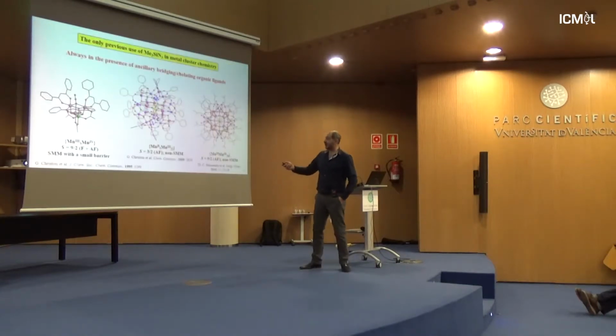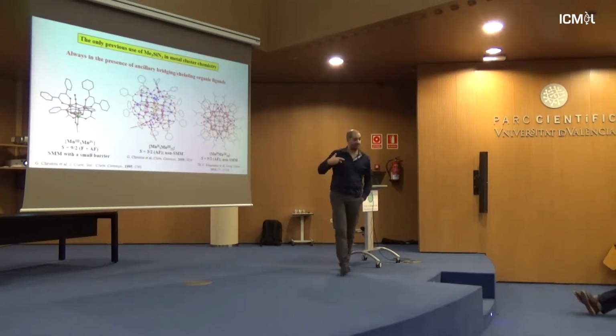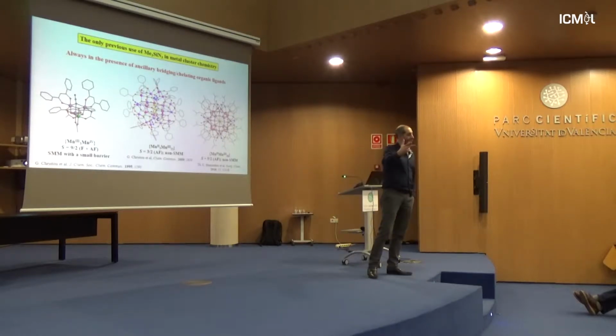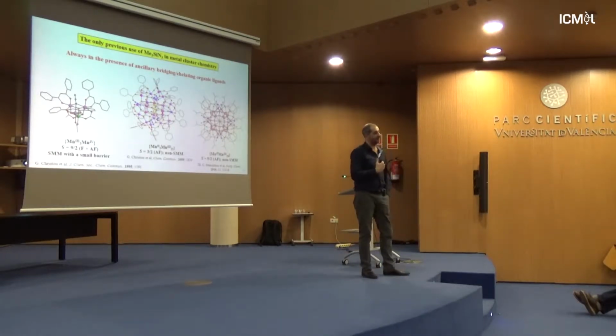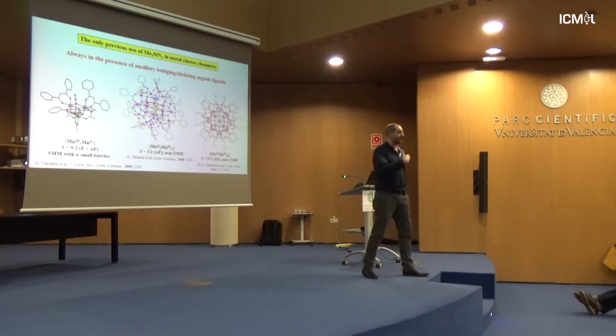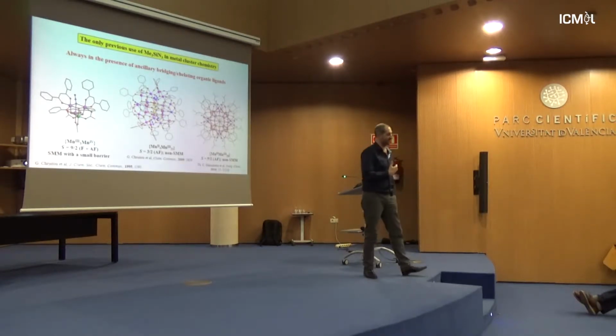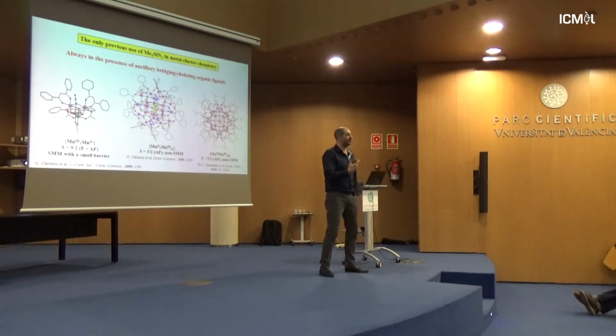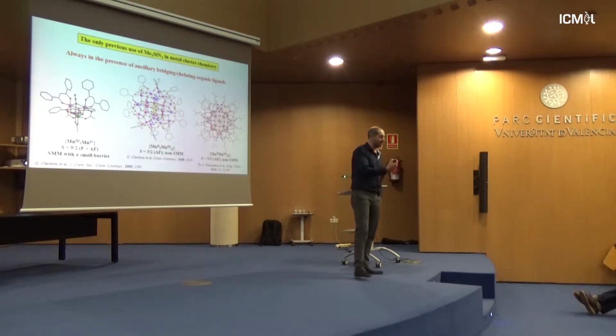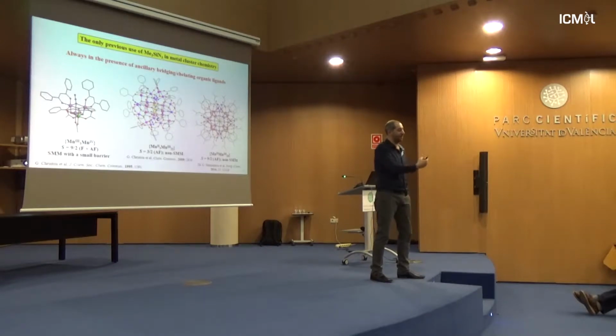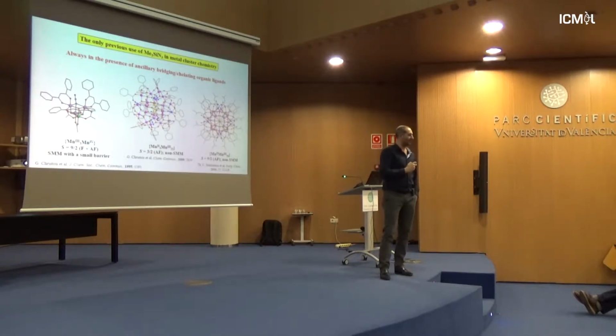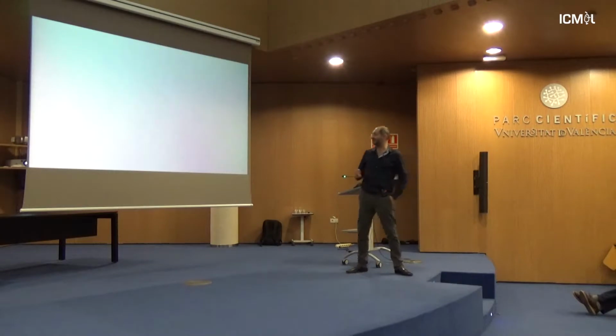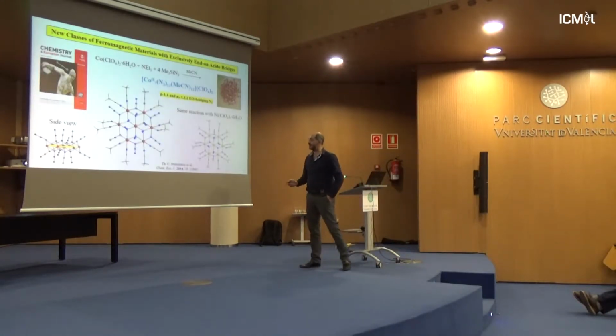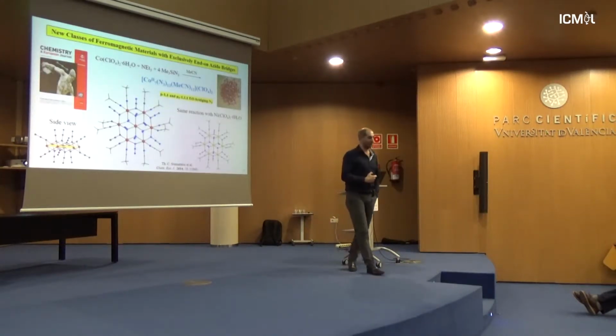So, the question here was to try to get this chemistry into a different level, try to remove all of these organic components and see if we can grow crystals of what we really hope to be a new class of inorganic materials. It took us more than 3 years to grow those crystals because the problem was exactly coming from what I've told you before. If you don't have organic component, it's really difficult to grow crystals of a molecular compound. But we figured out what was the key to that challenge, and we were able to make these new classes of pure inorganic materials.